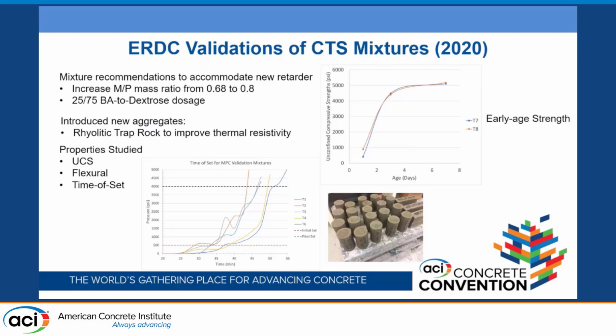We increased the magnesium phosphate mass ratio from 0.68 to 0.8 as part of this change, so we altered the binder some. And then we introduced a new aggregate, rhyolitic trap rock, to improve thermal resistivity. There wasn't a whole lot of science behind it, but we just know that that is a type of aggregate recommended in the UFGS standards, and so we picked it, hoping that it worked out, and it eventually did.